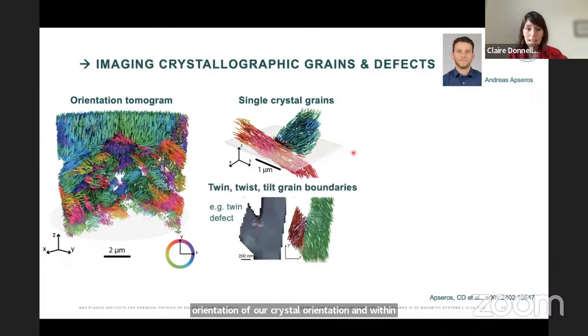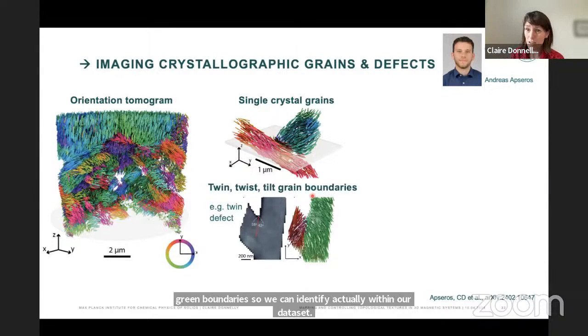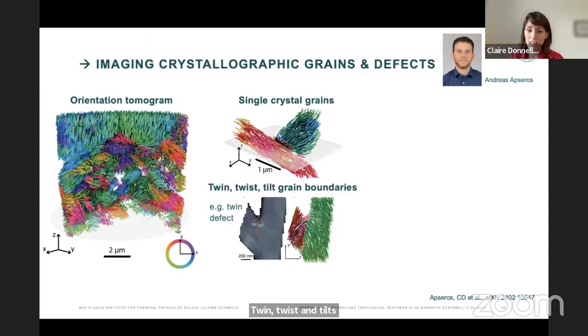But we're also able to identify regions where we have grain boundaries. So we can identify within our data set twin, twist and tilt grain boundaries. We have a twin grain boundary here. And we can see that even though in the electron density we were not able to really identify any loss or decrease in the electron density at this boundary, we can nicely identify it from the crystal orientation.